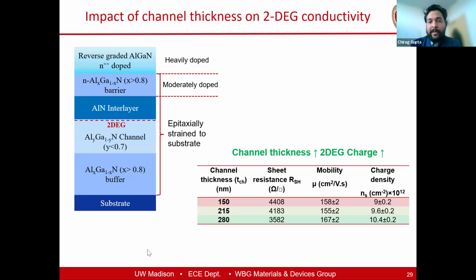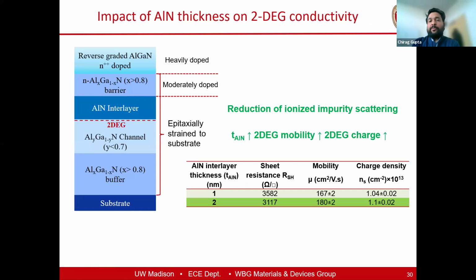So another optimization that we looked at was the aluminum nitride interlayer. In gallium nitride design, aluminum nitride is extremely important. This interlayer makes a huge difference in mobility. However, you'll see here the mobility difference is only 10%, and this is probably because the channel is in an alloy instead of a binary material. But all in all, you can see that we were still able to reduce our sheet resistance to close to 3000